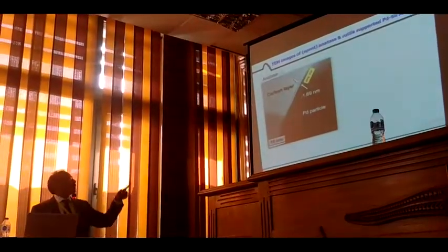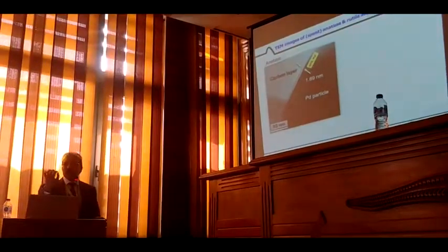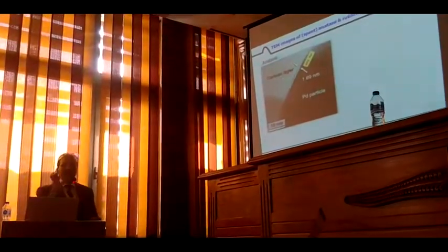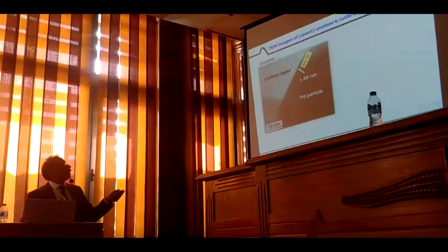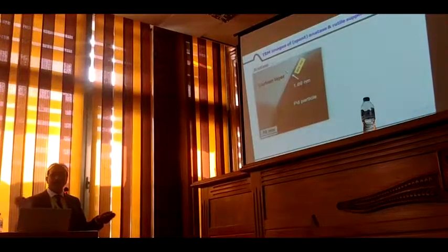So we just showed titanium anatase and rutile. Not only does the amount of coke deposition differ, the nature of coke also matters a lot. There is a huge difference in the nature of coke. When we deactivate, anatase is a deactivating catalyst, rutile supported catalyst is a non-deactivating catalyst.